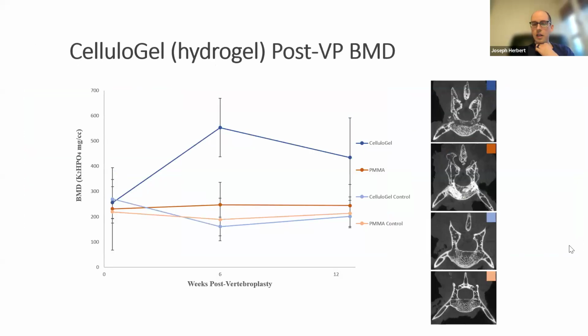So one of the interesting things that they found using this hydrogel as a vertebroplasty substance is that over time the bone mineral density actually improved in these rabbits. These were representative CT pictures. You can see on the top here, they've started calling this hydrogel CelluloGel now. You can see where they injected. But if you look at this cancellous bone compared to the relevant controls here and here that were injected with saline, you can actually see an increased density of these trabeculations here compared to here. And you saw this a little bit with the PMMA, but to a greater degree with the CelluloGel.